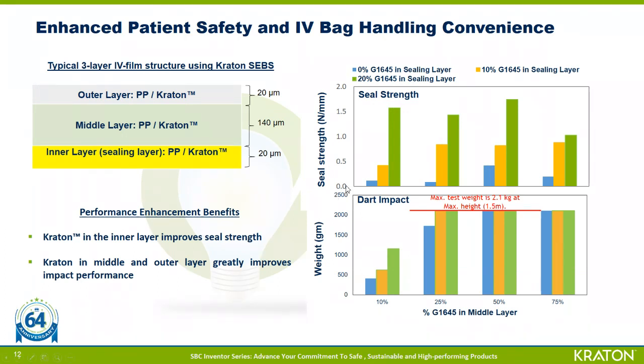Here we present an example of medical films in an IV bag application. A typical 3-layer IV bag structure is shown here, where each layer is composed of a Kraton SEBS and polyolefin. In this example specifically, we have prepared films using the Kraton grade G1645 blended with polypropylene. The type of polypropylene, for example, if it's homo or random copolymer polypropylene, was selected based on which layer it was going into. The total thickness of this film was 180 microns, which is a typical film thickness in this application.